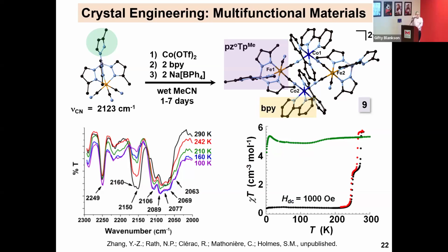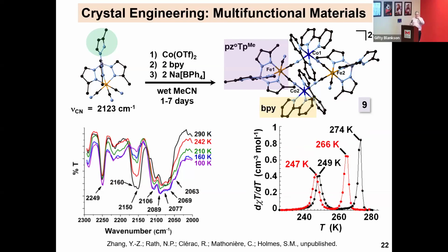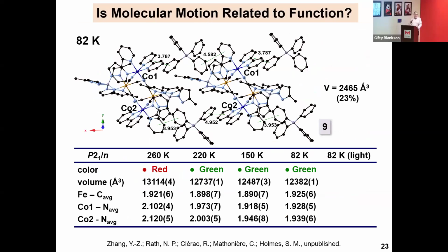And if you look at the crystallography, you have one iron center and one cobalt center that have a different number than the other two. That means they are crystallographically independent. And from the magnetic data, it suggests that maybe they have different energy costs for their electron transfer because they have different bond distances and angles. All right, showing you just the derivative to show you have two different thermal hysteresis. You have one with a very large one, suggesting you have lots of cooperativity between molecules. And then you have a much smaller one, suggesting you have very little. So as you can imagine, big thermal hysteresis takes lots of energy. Small thermal hysteresis, very little. Right? And so on that working hypothesis, you can see that crystallographically.